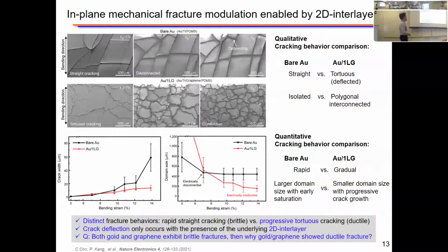So I'll just move on to this. We look at the fracture surface of the metal to see why we're seeing this type of phenomenon. The top panel shows a series of SEM images comparing the crack behavior under bending deformation. The top three panels show the conventional metal electrode architecture, where we have a thin film of gold, a thin layer of titanium, and PDMS. On the bottom, we insert graphene at the interface. As you can see, without graphene, the cracks propagate straight, resulting in relatively large areas of isolated fracture domains. However, with graphene, cracks propagate with local zigzag fluctuation, resulting in tortuous cracking behavior with polygonal interconnected fracture domains.